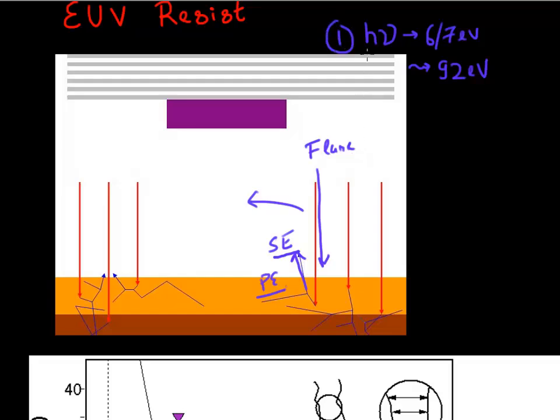The second challenge with this EUV resist is that since EUV generation as well as the optics of EUV is so inefficient, they have to deal with a much lower dose. So typical deep EUV resist, they are designed for a dose in hundreds of millijoules per centimeter square. But since EUV is such an inefficient process, people want to design resist which requires a much lower dose.